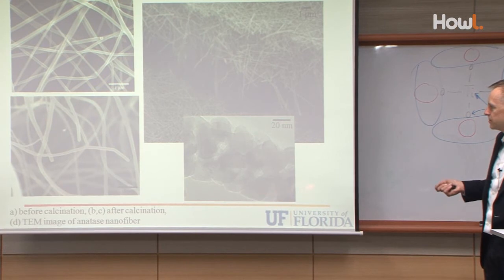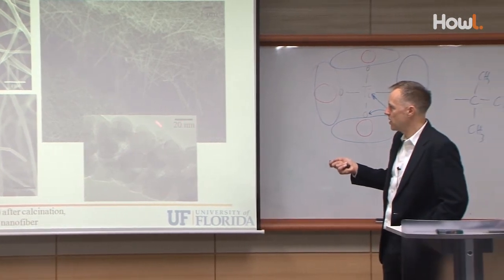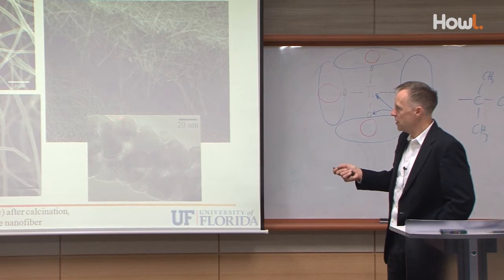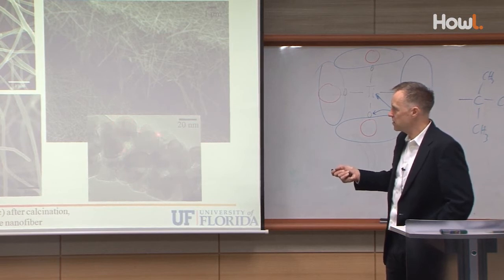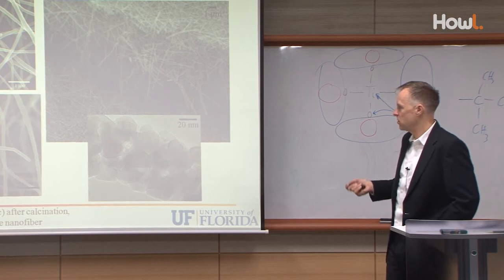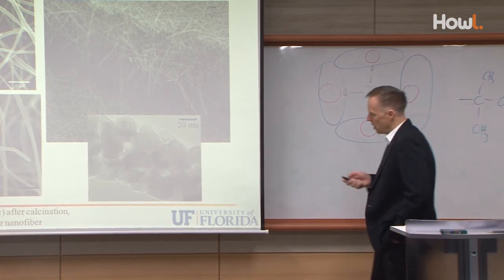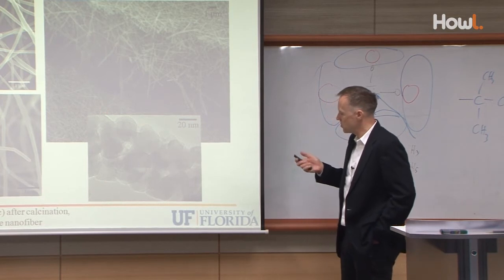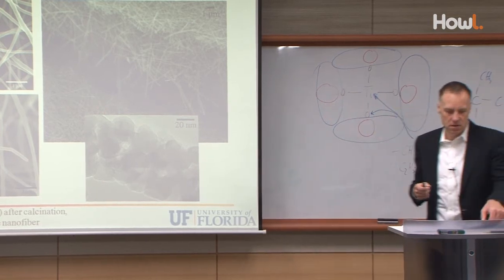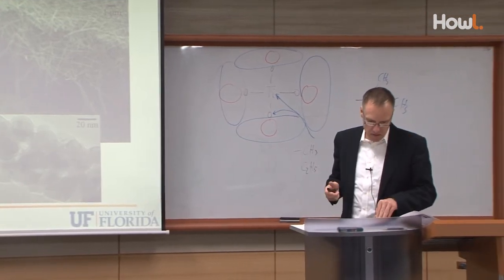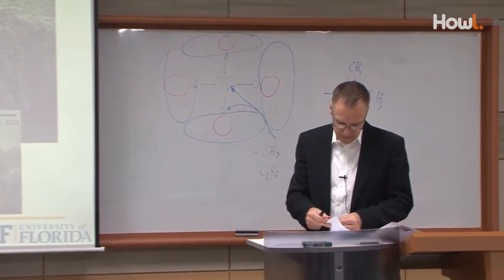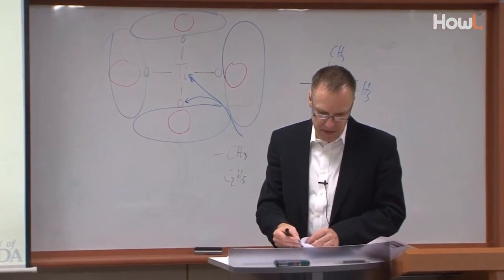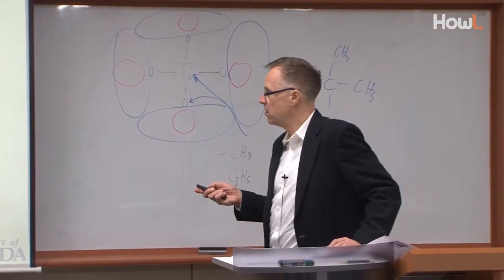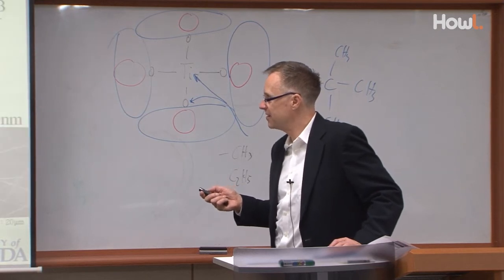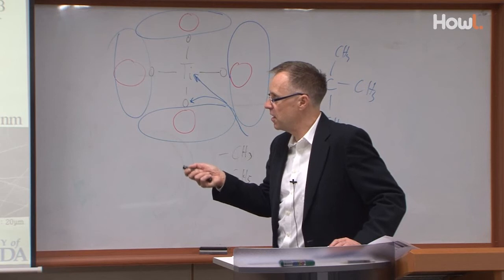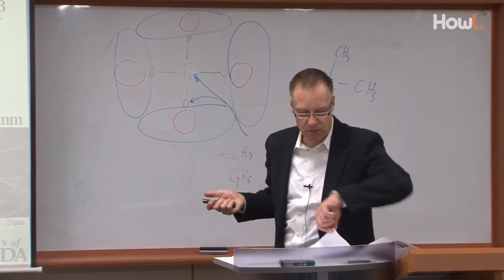And here's a fiber. This is one of the thinner ones. And with a 20 nanometer bar, and this is, of course, a TEM picture now. And you see you get all this porosity in here. You have grains formed after heat treatment. And so these fibers cannot be too strong. But you see we can actually make really small structures. And this allows you to make similar compounds by, that's the wrong direction, sorry, by using different precursors here. Yeah? So sol-gel is available for a variety of compounds.